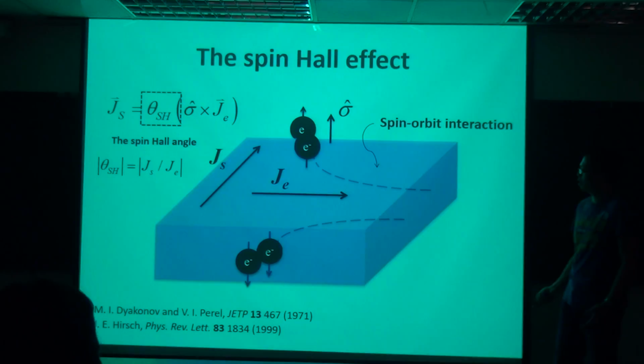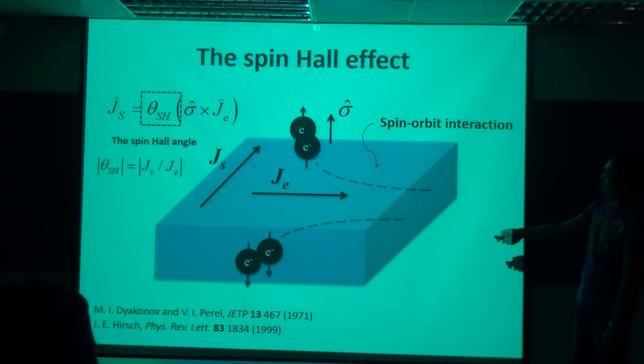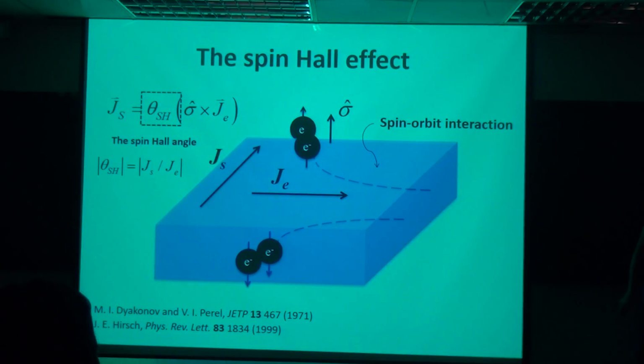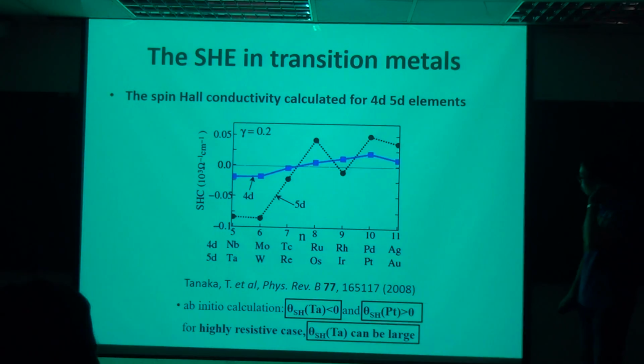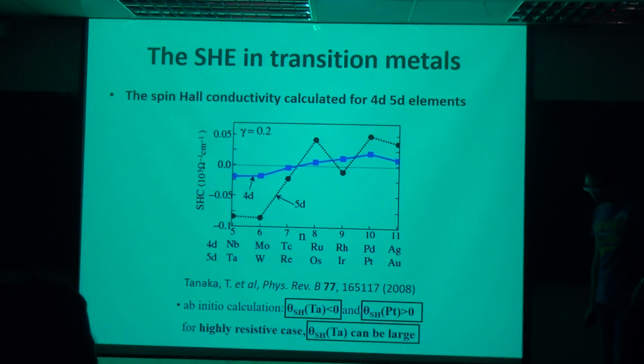Just like for people who work in the solar field, we want efficiency higher than, say, 30% or something like that. And we want this to be larger than 100%, because again, this ratio is just a definition, so it can be larger than 100%. And actually, in the past, like 2008, there was a lot of theoretical work done, even here in NTU. He did a lot of work on the spin Hall effect, especially in platinum, from first-principles calculations.